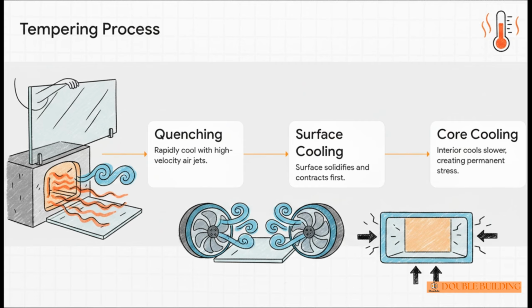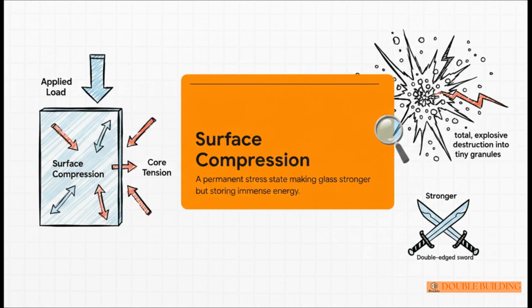Now, the outer surface of the glass solidifies and contracts first, but the liquid interior cools much slower, and as it tries to contract against that already rigid outer surface, it creates an immense, permanent state of internal stress. And this creates what we call surface compression. The surface is locked in compression, and the core is locked in tension.